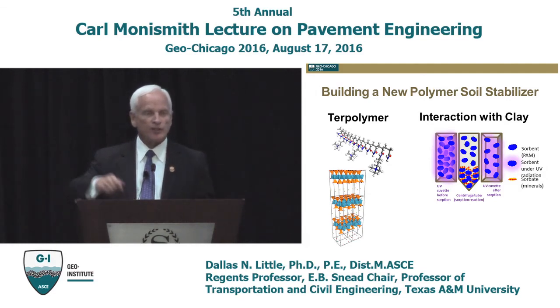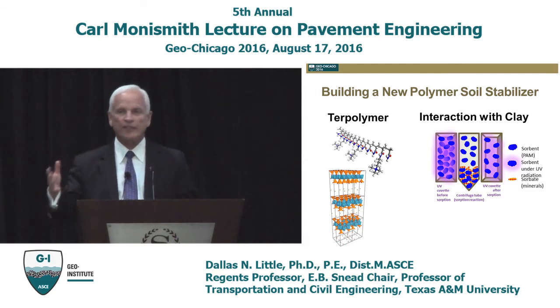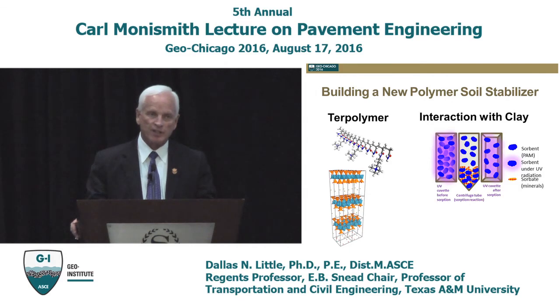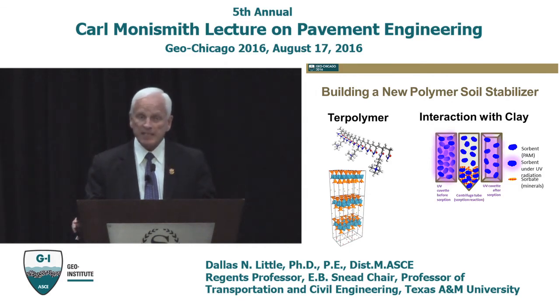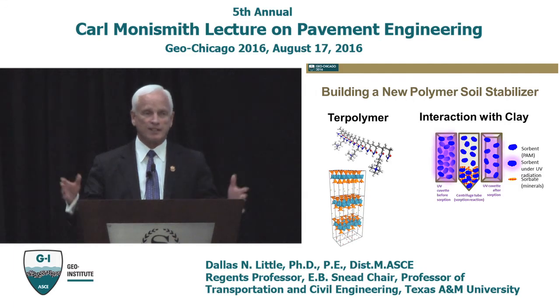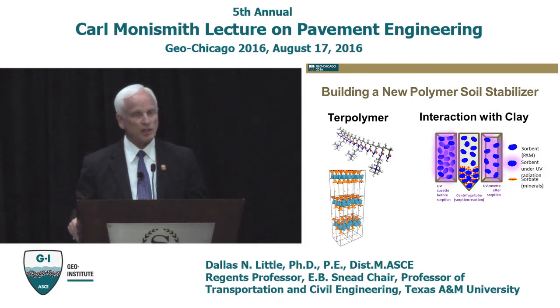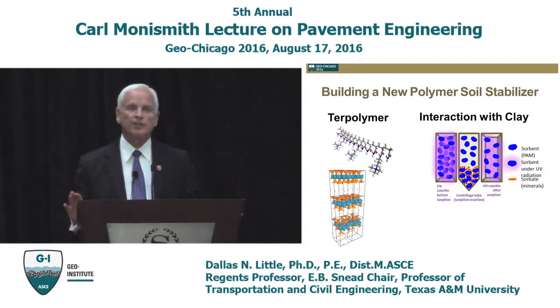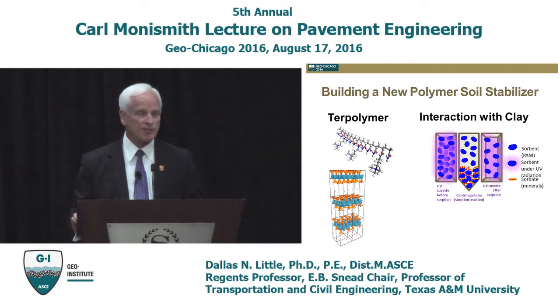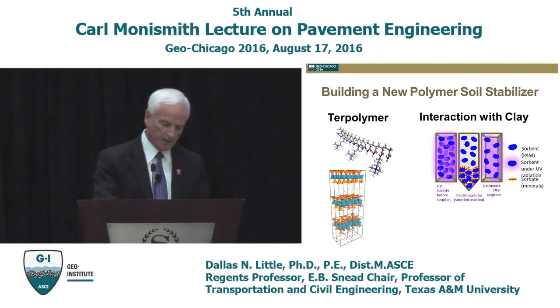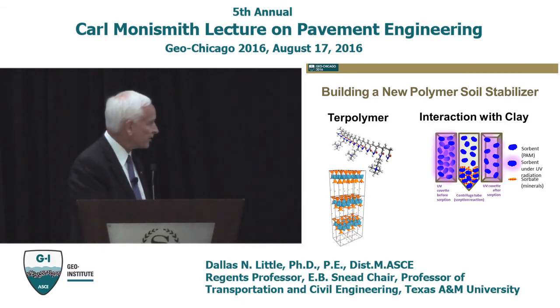If you do a fracture energy calculation, the fracture energy is about 3 times that of the cement stabilized material, meaning that its fatigue life is greatly enhanced. So we're still working to make sure that it's not susceptible to the effects of moisture, but this terpolymer and these types of polymers tend to have a lot of potential. And also the percentage of additive is shockingly small, about 2.5% versus maybe 4 and 5% for some of the other stabilizers. So something on the horizon that's pretty interesting.